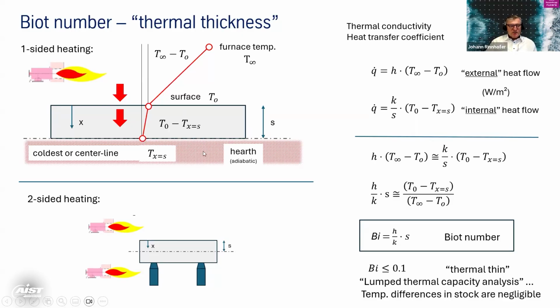When you have the slab sitting on an adiabatic hearth, that means this is a kind of insulated hearth, there's no energy carried over that line into the hearth, so to say. This is an idealistic view of this slab sitting on an insulated hearth. So we have external heat flow and internal heat flow in the slab. And when we say external is equal to internal, we end up with this equation here. Then what we do next, we put all the temperatures on one side, the right side, and all the other properties on the left side. So we end up with h, the heat transfer coefficient, divided by the heat conductivity lambda times S, the thickness of the slab. And that is the Biot number. That describes the thermal thickness of the slab. So it can be thermally thin when Biot is less than 0.1.